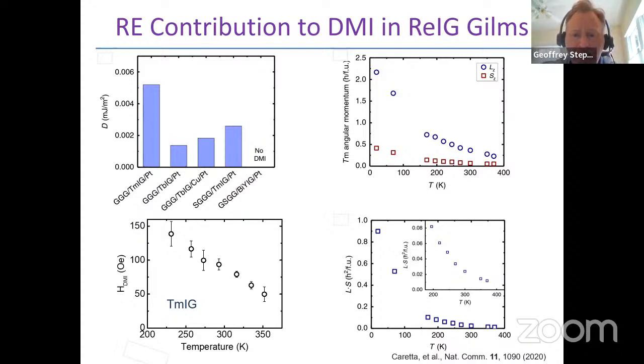So really the data indicate so far that we need a broken interfacial symmetry in these systems, but the spin orbit coupling that drives the DMI in this system is not coming from the metal, but it's coming from the rare earth that's in the garnet itself. So we're still trying to understand the origin of this, but that seems to be a particularly important ingredient.